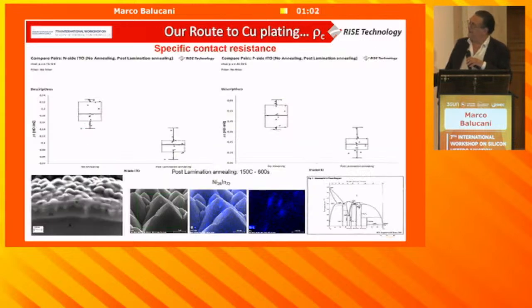And the nice thing is that, if you see, when we deposit the nickel, we are covering the indium balls, and then we do a simulation of the lamination process at 150 degrees, and at 150 degrees, mainly what you are forming is a eutectic, okay?